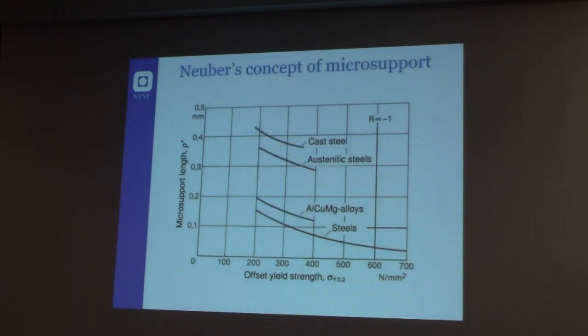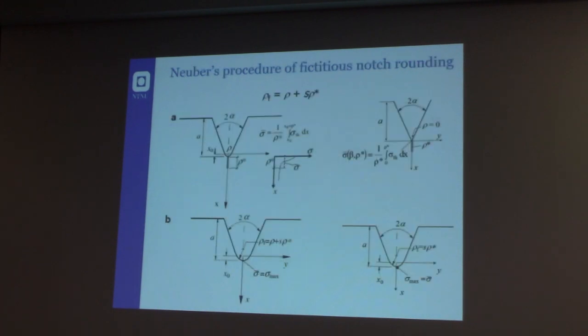The microstructural support length was discussed by Radai for different materials. For steel and austenitic steel, we are in the range of 0.3 to 0.4 millimeters as a critical support length of the material. The Neuber procedure of fictitious notch rounding can of course also be applied to a sharp case, because if you have a sharp case, the real radius term, which is equal to 0 in the initial model, is simply dropped, and in the fictitious notch radius approach you have S multiplied by rho star. This method wants to avoid the singular behavior, the singular problem of stresses tending to infinity close to the crack or notch tip.